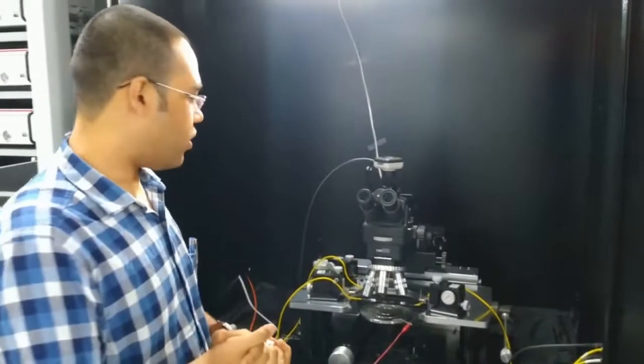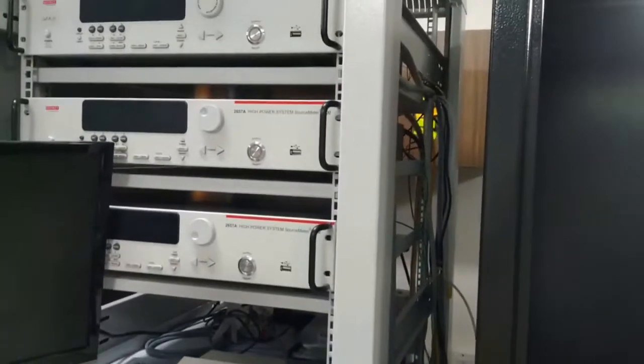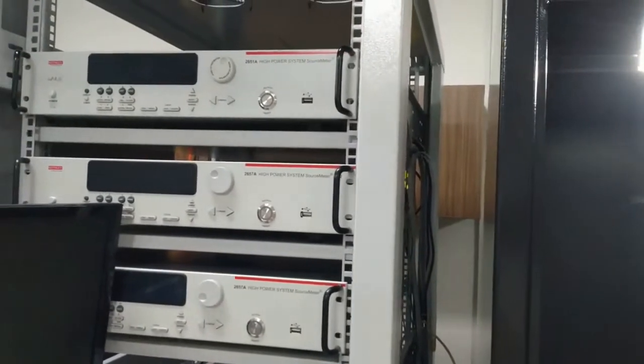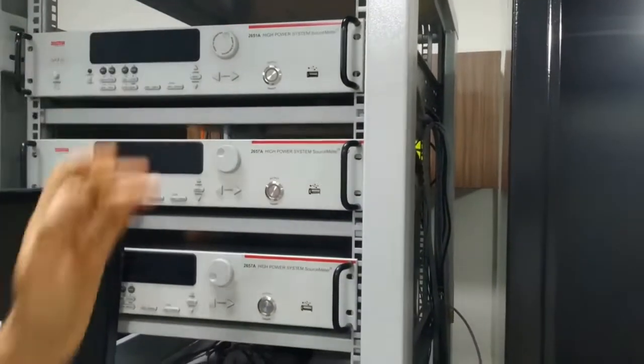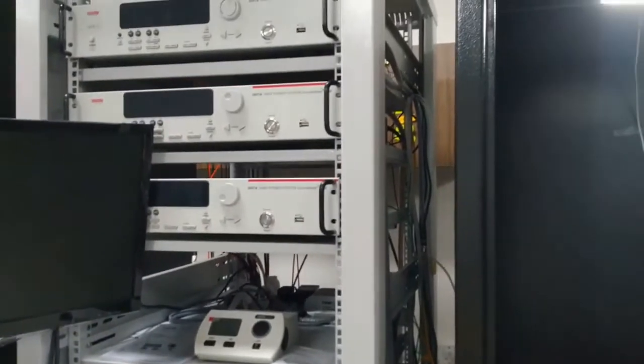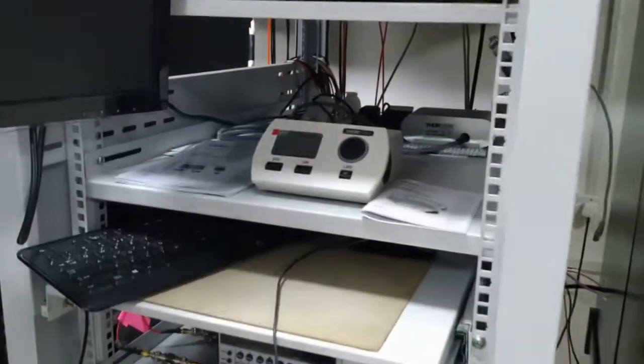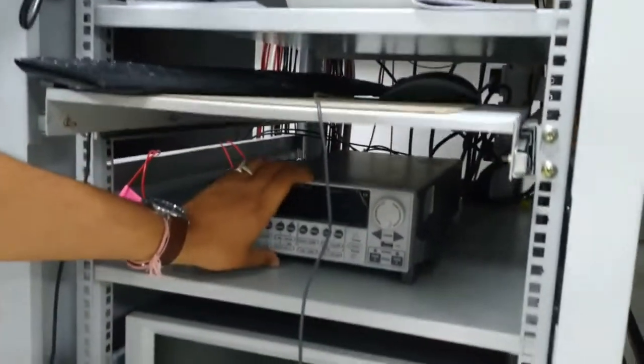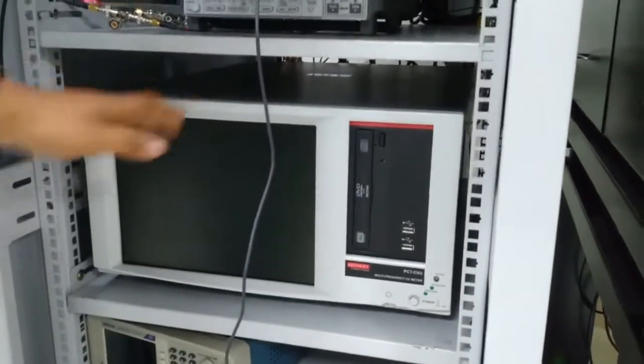This is the hot carrier reliability setup in which we stress the devices over a wide range of stress times from ultra-short times to long stresses using a dedicated set of high power SMUs. Immediately after stressing these devices for a certain amount of time, we measure the basic health parameters of the devices using optical excitations and moderate power SMUs for IV measurements and capacitance voltage measurements to identify evolution of traps and defects in the devices.